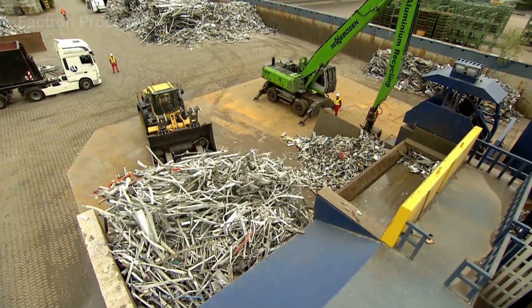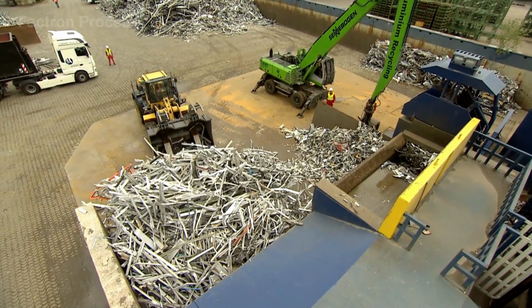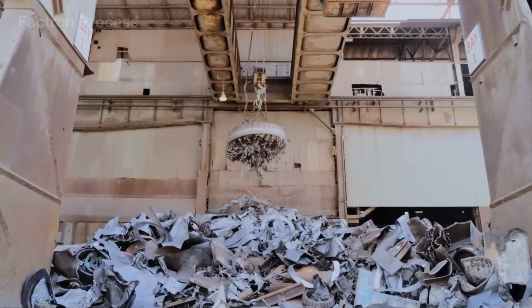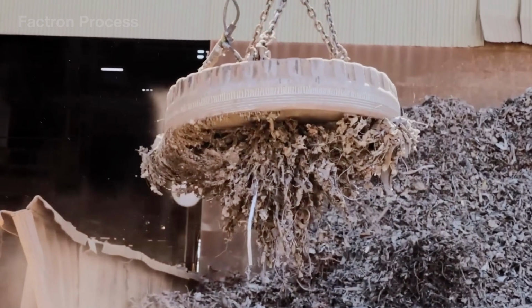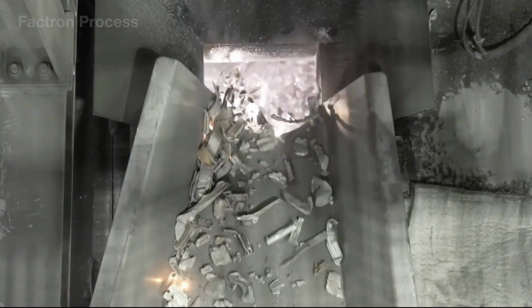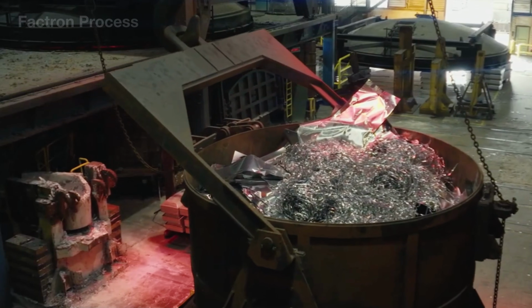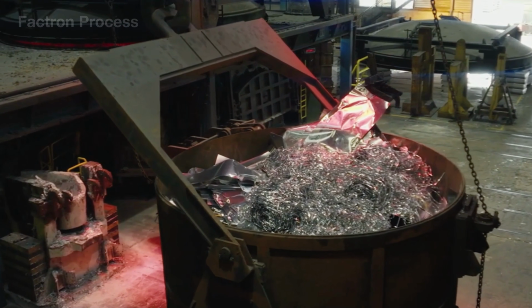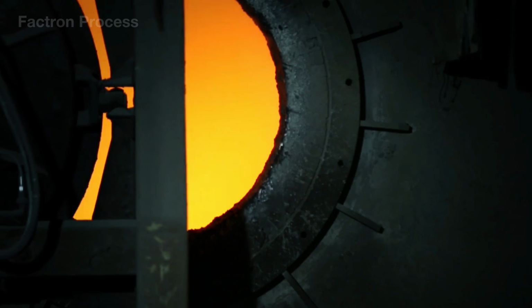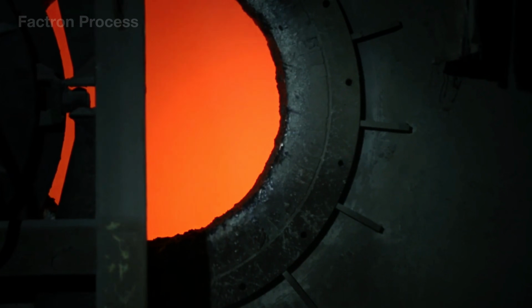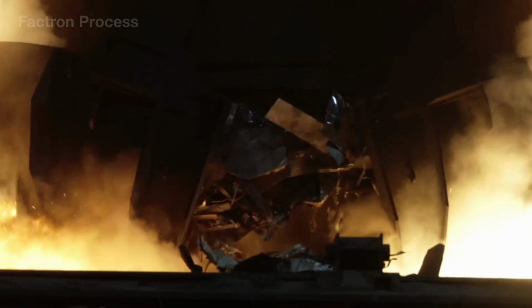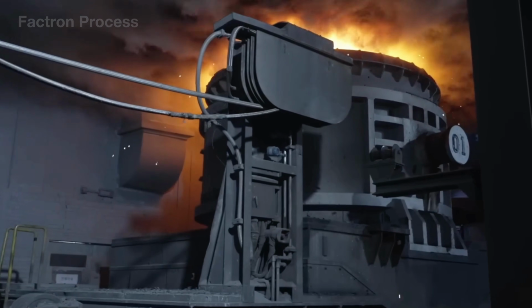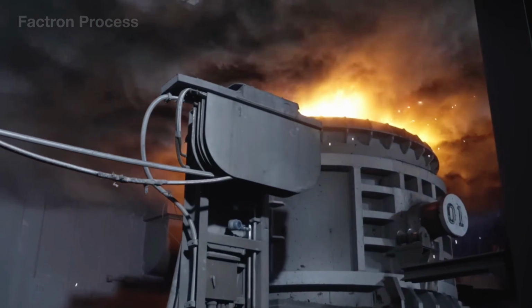Once separated and cleaned, aluminum recovered from the aircraft fuselage is fed into a furnace at approximately 660 degrees Celsius or higher, hot enough to transform the solid alloy fragments into molten metal. During this process, residual paint, grease, and other contaminants rise to the surface as dross and are removed. However, aerospace aluminum cannot simply be melted and poured into a mold.